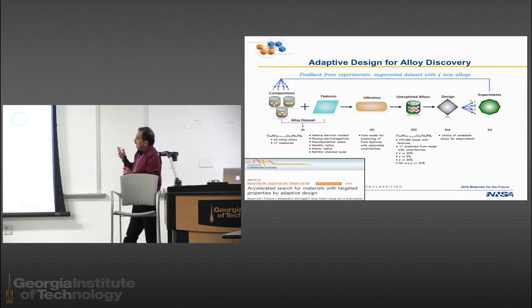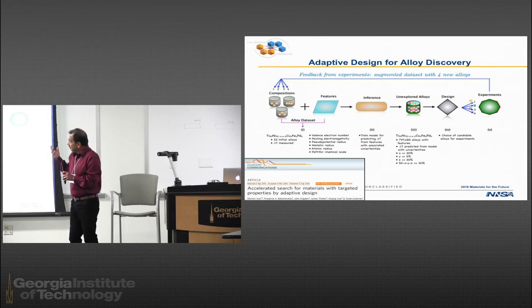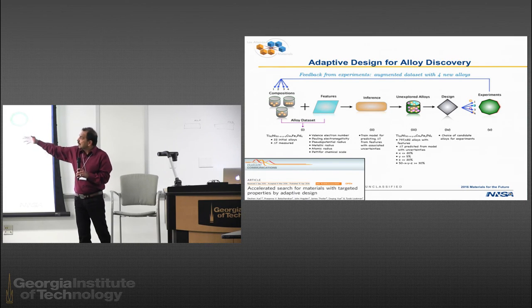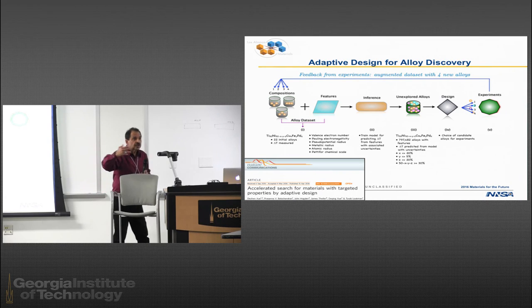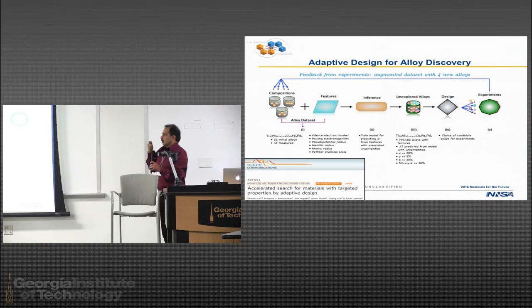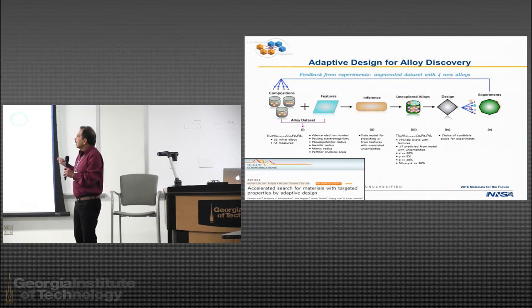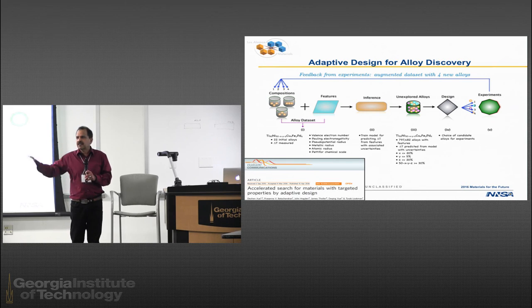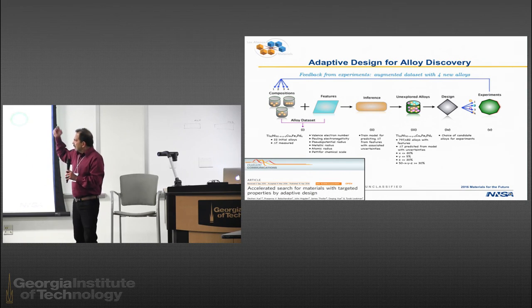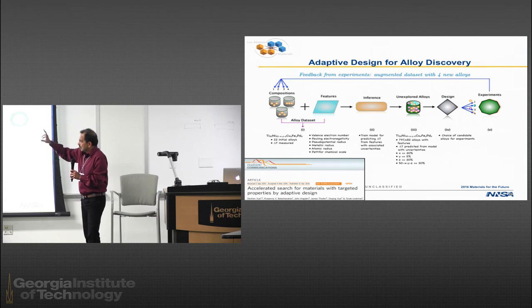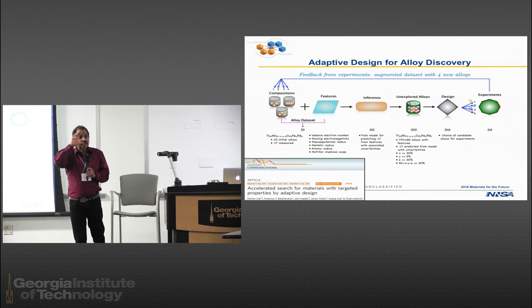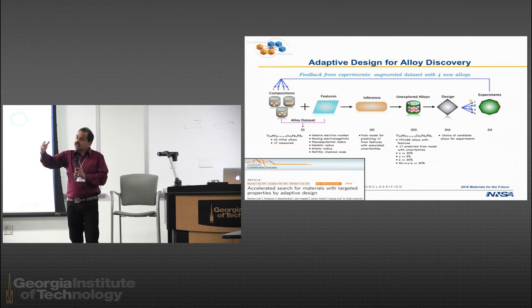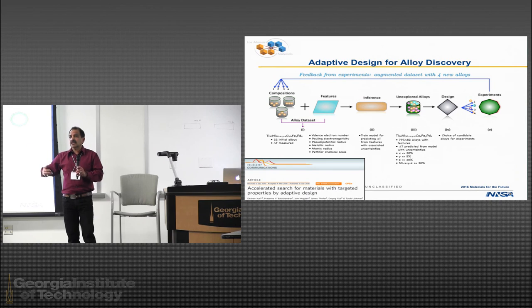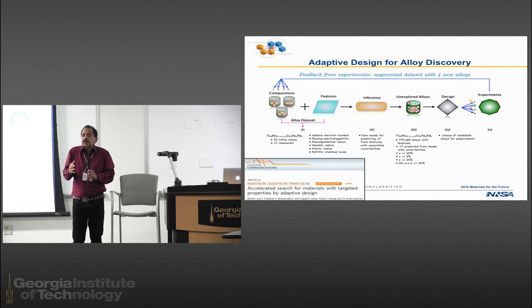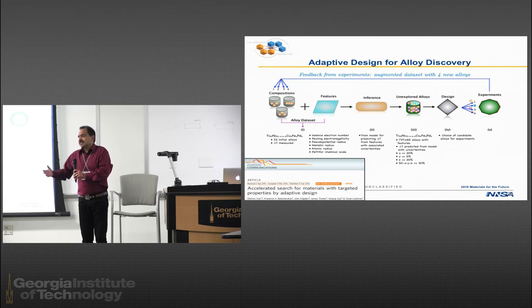So the strategy that we came up with is this. We start with our compositions. We identified the material descriptors or the features. And here, domain knowledge was very important. We knew from the literature that things like the valence electron number per atom is important. It affects the thermal hysteresis. It affects the transition temperature. There's a lot of work published. The atomic radii of the species is also important. So we down-selected a set of features. We didn't want the feature list to be too large because that really explodes the degree of difficulty in terms of the high dimensionality of the problem. You want it to be small, yet you want it to be able to say something.